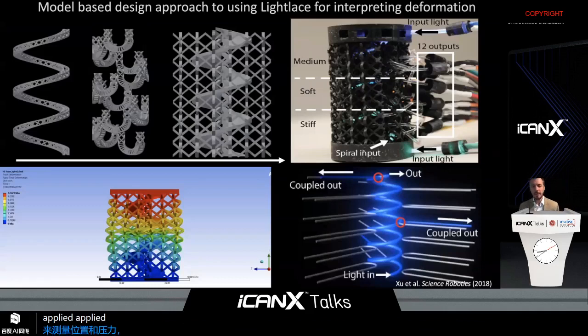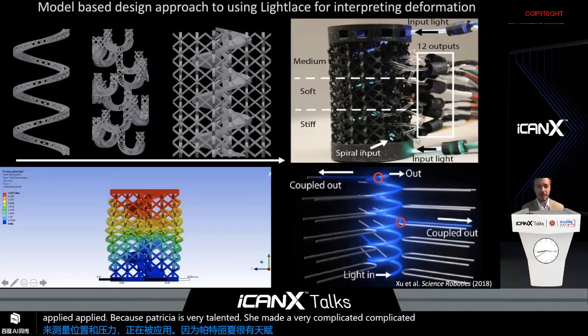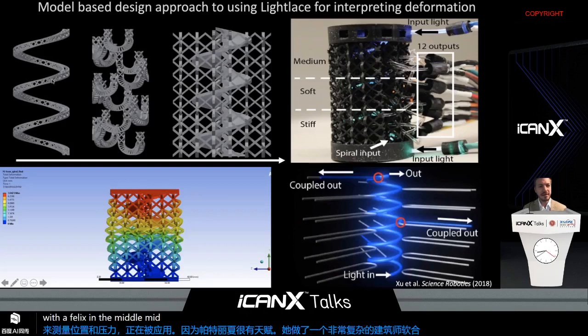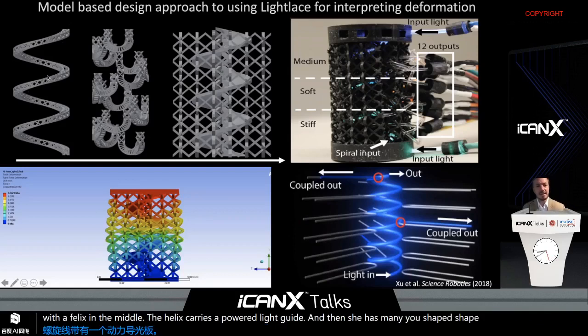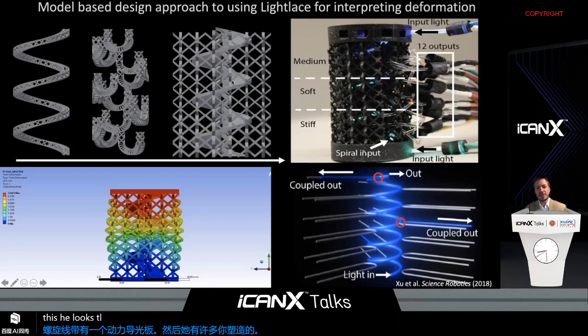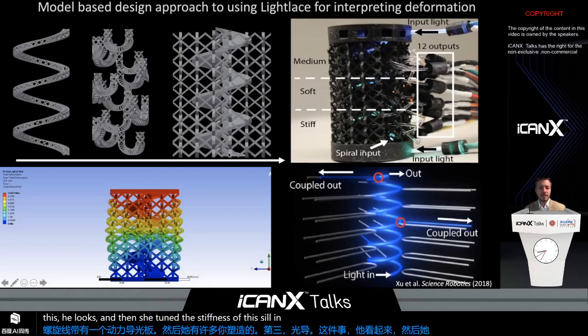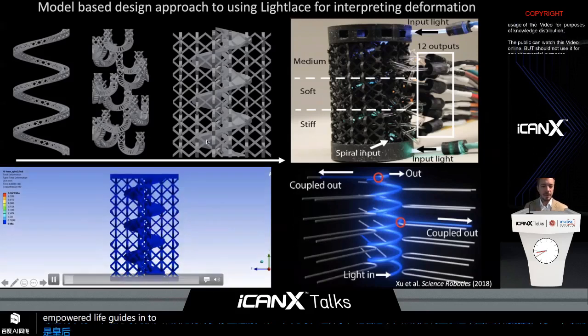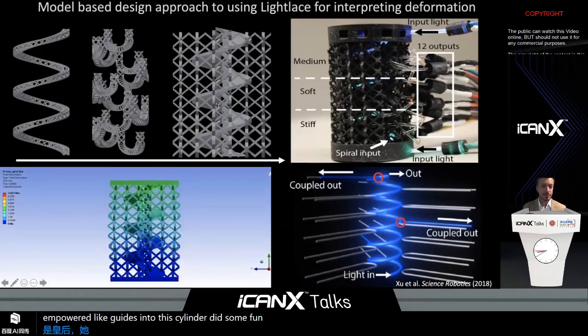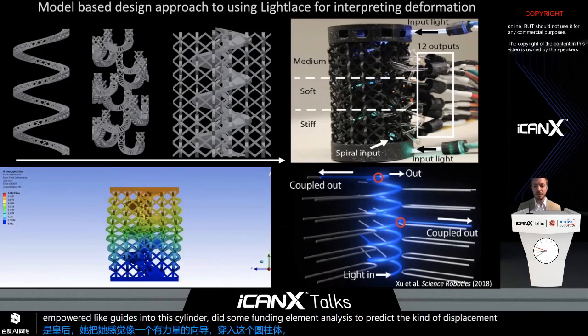Because Patricia is very talented, she made a very complicated soft printed architecture with a helix in the middle, and that helix carries a powered light guide, and then she has many U-shaped unpowered light guides incident on this helix. And then she tuned the stiffness of this cylinder with another helix that is quite thick. And then she threaded her powered light guides and unpowered light guides into this cylinder, did some finite element analysis to predict the kinds of displacements she would get for a particular pressure.